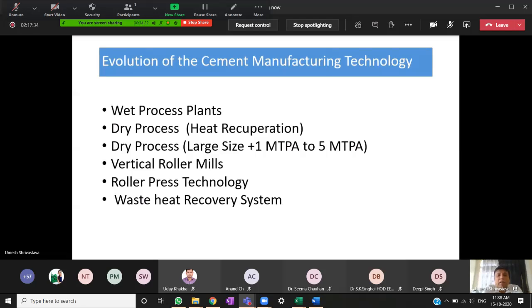So the higher the size means you have to have higher storage space for the raw materials, higher capacity of mines. Everything has to multiply by at least 4 to 5 times mechanically. During those times, most of the grinding was done by ball mills. Then vertical roller mills came somewhere in between. Then there is roller press technology, which has also evolved.